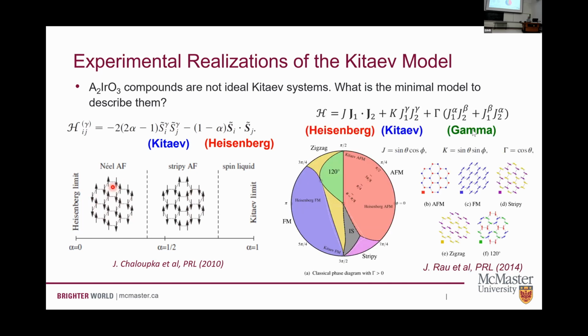If we throw in this gamma term, the symmetric off-diagonal exchange, it becomes even richer. And now we've got about 5 different ordered states that we can tune our way through as we change the balance between these Heisenberg and Kitaev states. Okay, so the takeaway message here is that which of these models we choose makes a big difference. And there are many of these states that are close together, which, if you're interested in making new materials or tuning new materials, gives you a lot of different phase space to play around with.